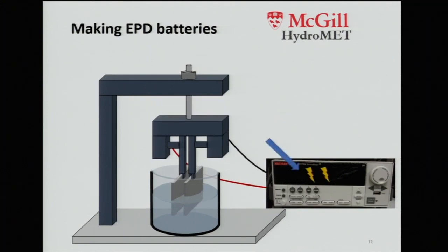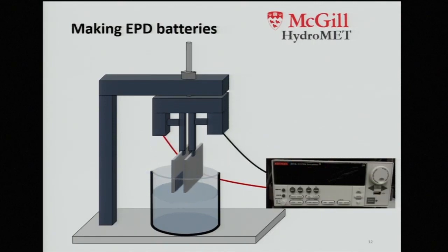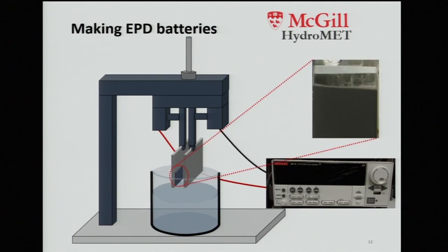And this is very brief. It's only done from anywhere between 5 to 15 seconds. This forces a coating to form. We can then remove the coating and allow it to dry and repeat this for as many times as necessary to create a thick enough coating. And this is what our coatings end up looking like. The black or gray part there is the aluminum foil that we submerged, and on top of it is the EPD coating that we just made.